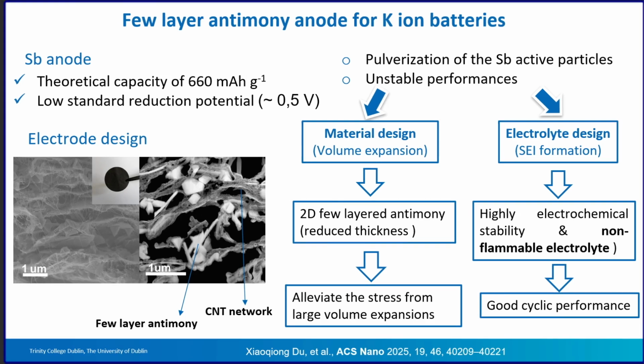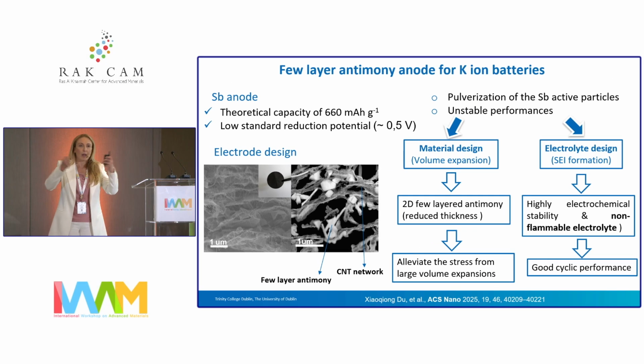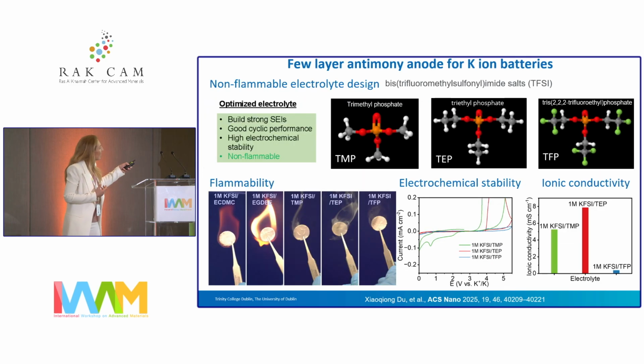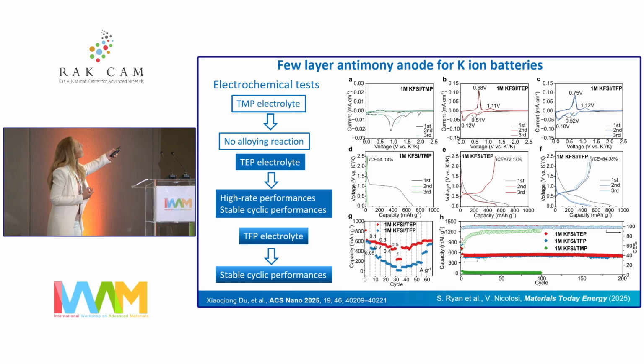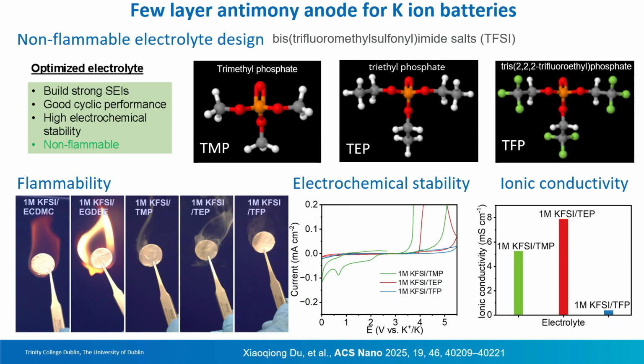And once again, one of the issues to solve there is the volumetric expansion and compression, so the massive stress from these very high volume expansions. Another thing that we focused on is the electrolyte design for the solid electrolyte interface formation. And we wanted to get away from flammable types of electrolytes. So this is the type of materials we work with. In this case, what we wanted to go away from was the flammability of some electrolytes. So we designed some TFSI type of salts with trimethyl phosphate, triethyl phosphate, and trifluoroethyl phosphate.